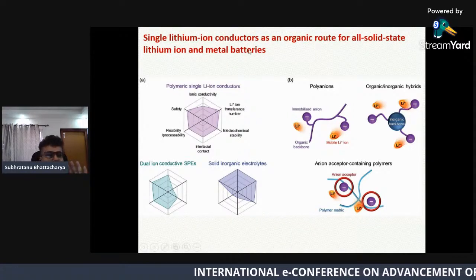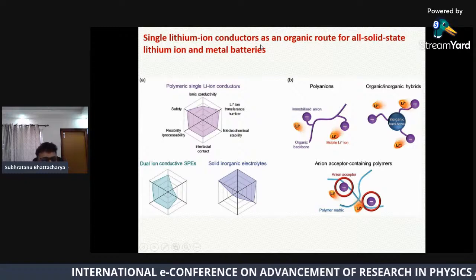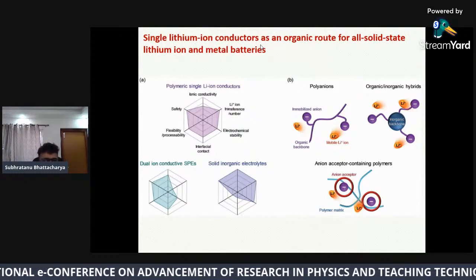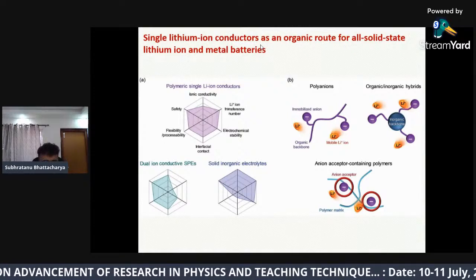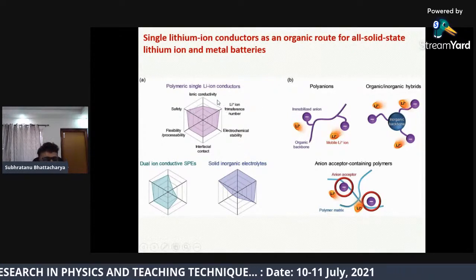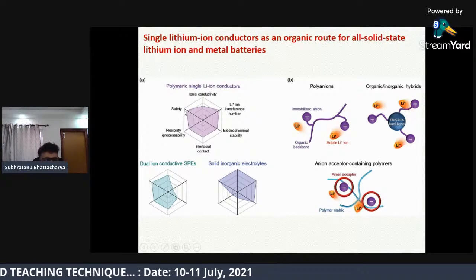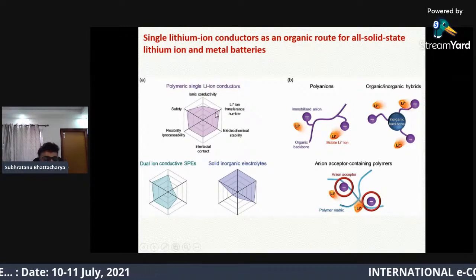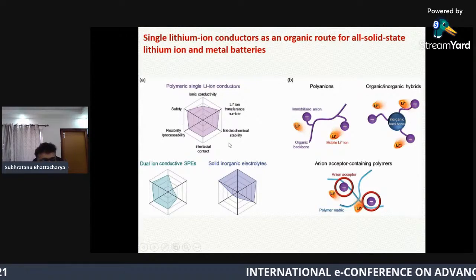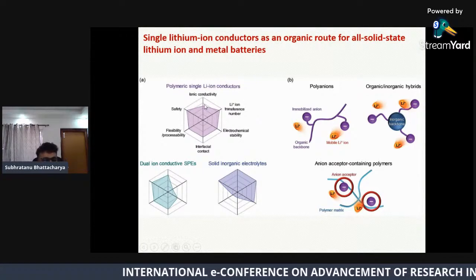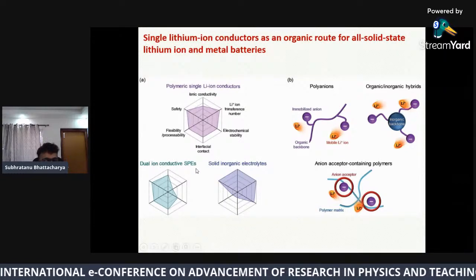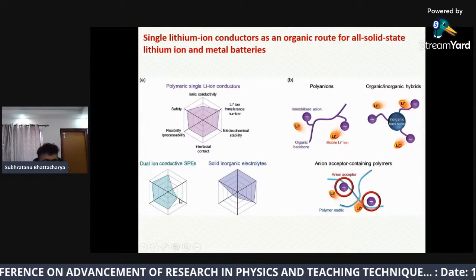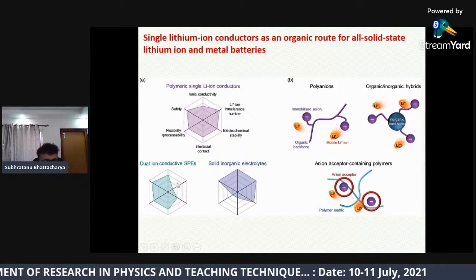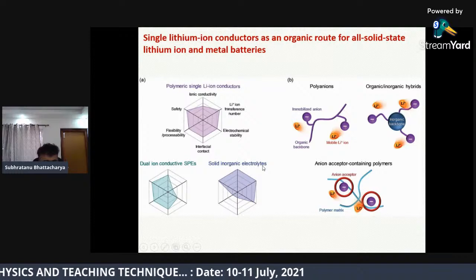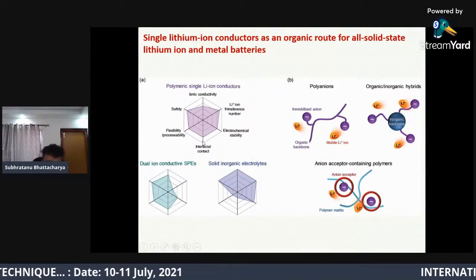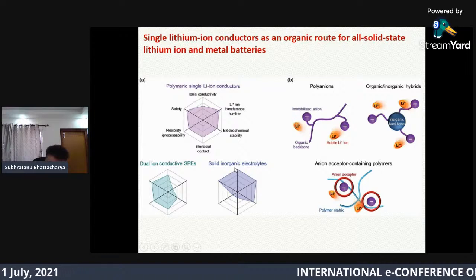That is called the single lithium ion conductor, where no anion will contribute to the conductivity. Only the cation will contribute. But the problem is that we are not getting high ionic conductivity, because we are not getting sufficient mobility to move the lithium ion. Everything is fine, only the ionic conductivity is very low. So this is the dual ion conductive solid polymer electrolytes, where you can see the lithium ion transference number is very low and other things are very low. Solid electrolyte, you can see the flexibility and interfacial contact are very low, but conductivity is high.